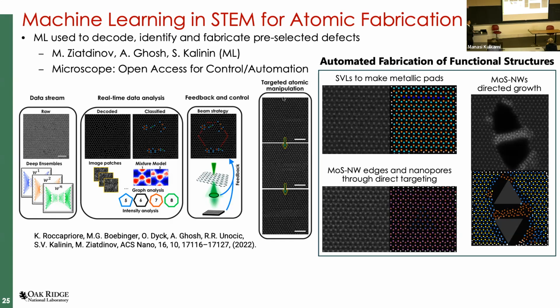So when you keep hitting with a beam, you're going to start moving things around, knocking things out, and creating either pores or Stone-Wales defects or just distorted lattice, whatever you need. So you can have this 6-fold symmetry that can change into 5-7 type rings. So you can match that really quickly.